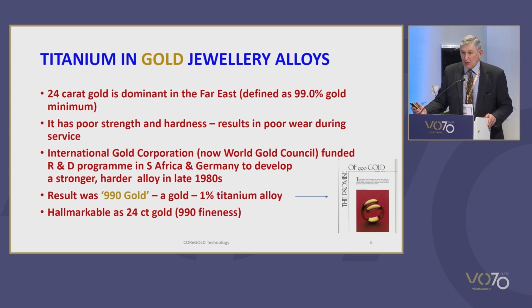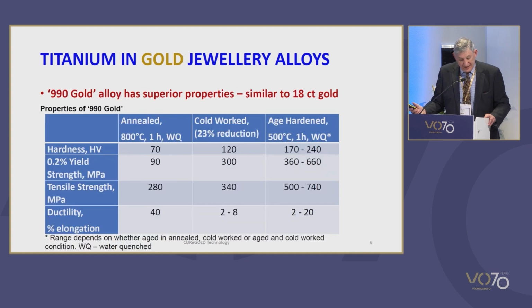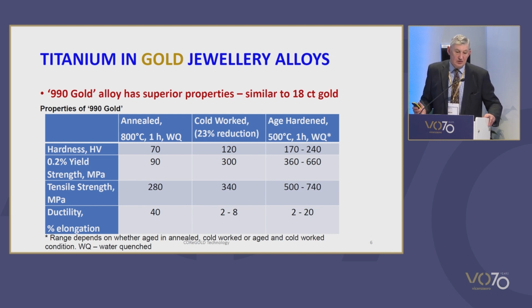Recognising this issue, the International Gold Corporation, which is now the World Gold Council, funded a research program in South Africa and Germany to develop a stronger, harder 24-carat gold in the late 1980s. This resulted in the development of 990 gold. It is a gold 1% titanium alloy. That is 990 fineness. So it is hallmarkable as 24 carat. It has mechanical properties considerably superior to 24 carat gold, approaching those of 18 carat golds, as we can see in the table. We can see that it has good hardness in the annealed, cold worked and age hardened conditions.